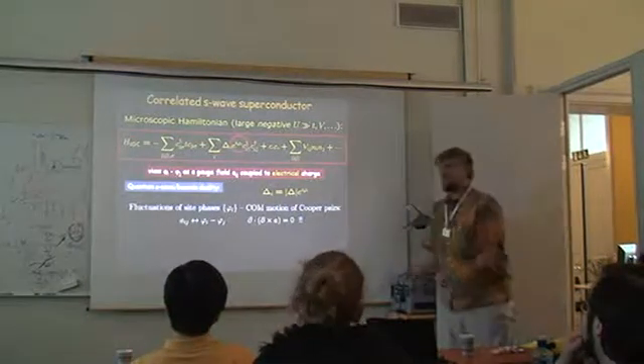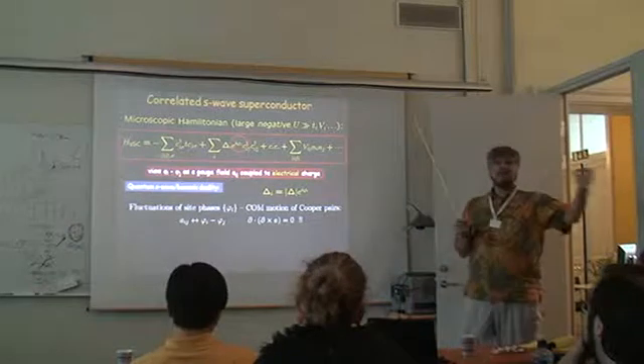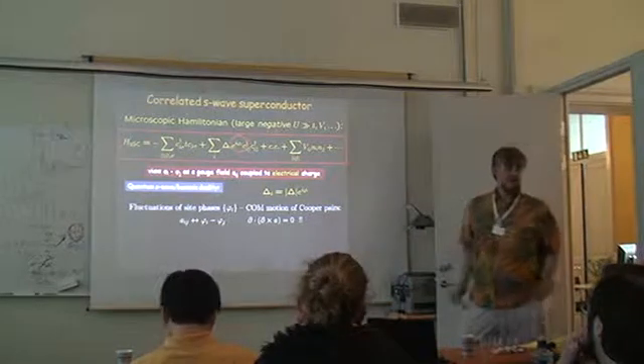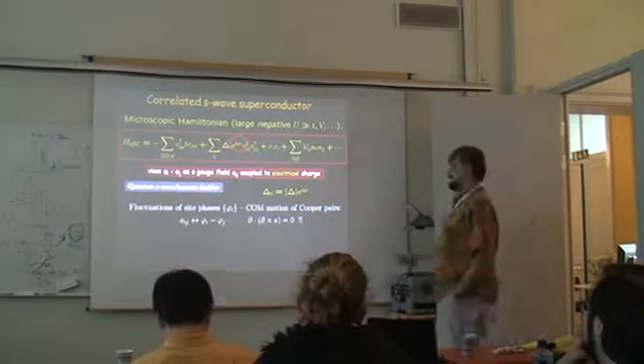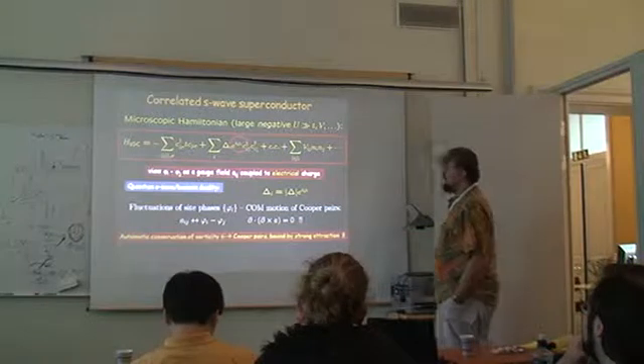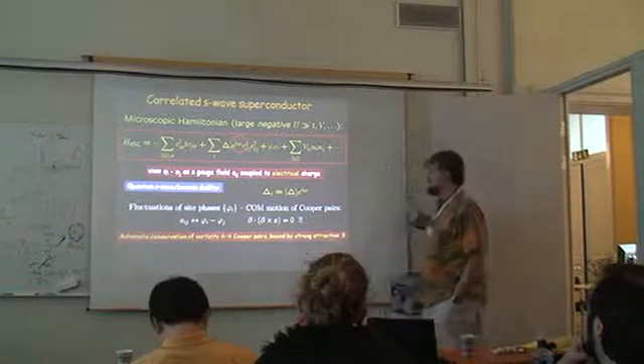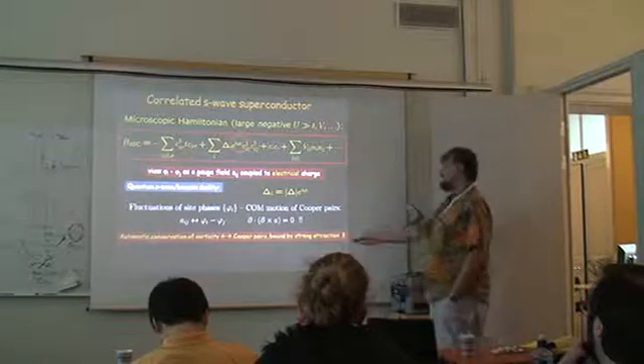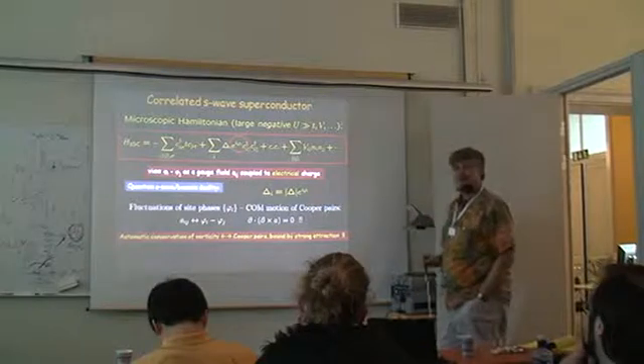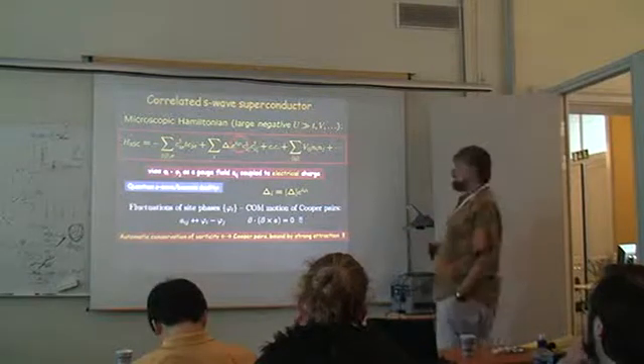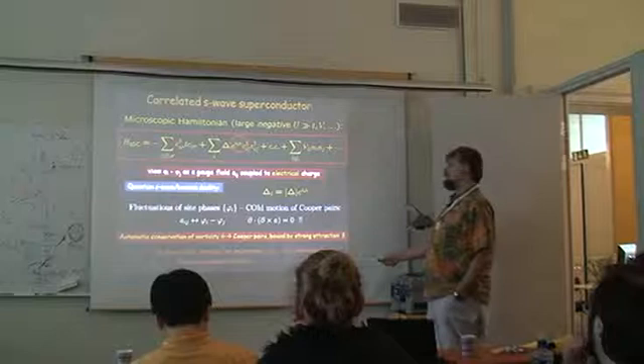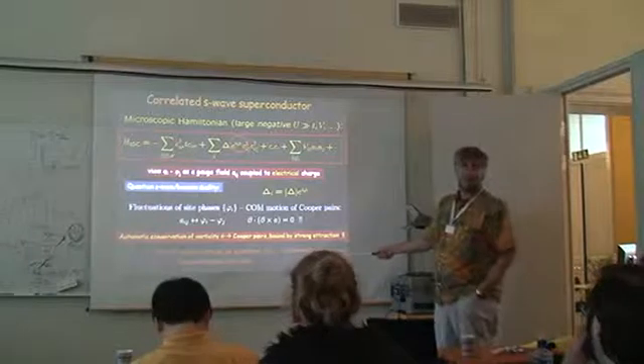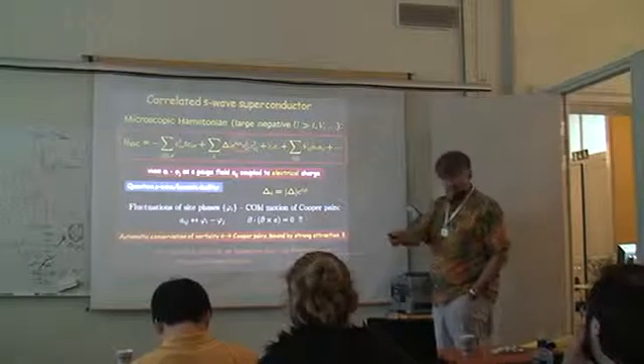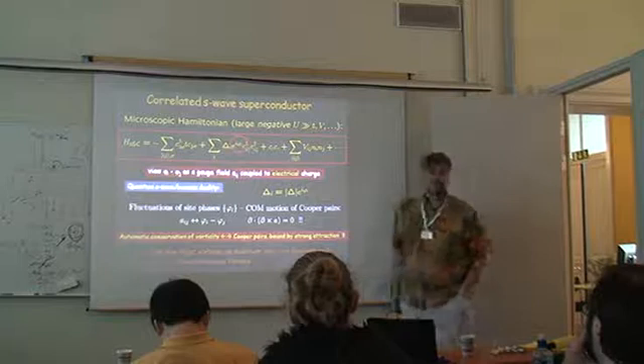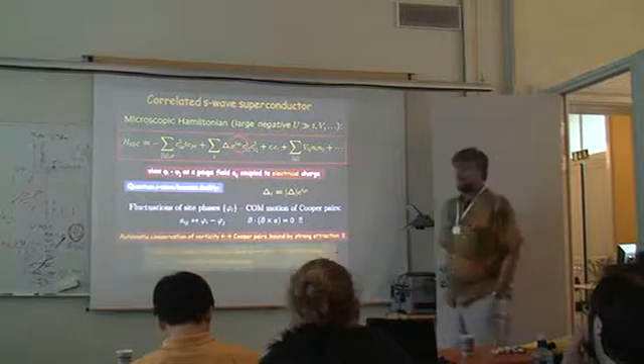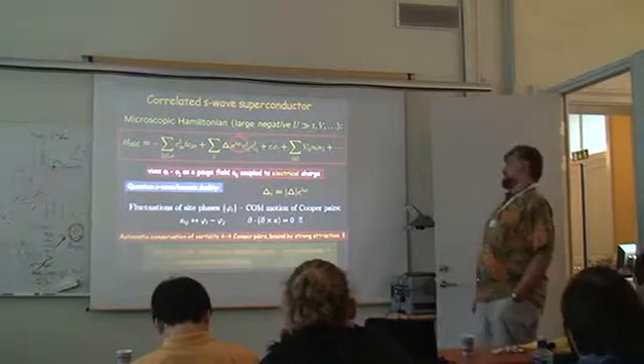This means that vortices behave as lines of magnetic field on the lattice, on this 2 plus 1 dimensional lattice. Why is that good? Well, that's good because we now can say that this conservation of vorticity is in fact strongly related to conservation of Cooper pairs, which it is, and therefore we can treat vortices as quantum particles, just like we could treat electrons or Cooper pairs in a Bose-Hubbard model as quantum particles. And this allows us to make some actually strong statements.